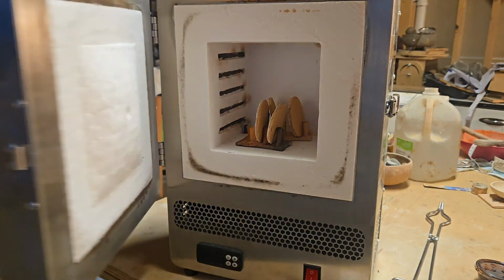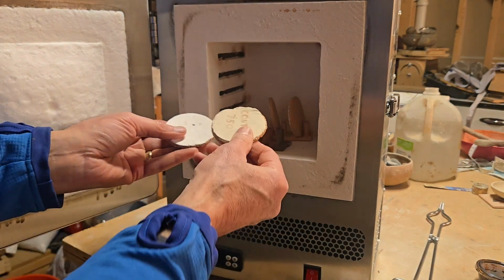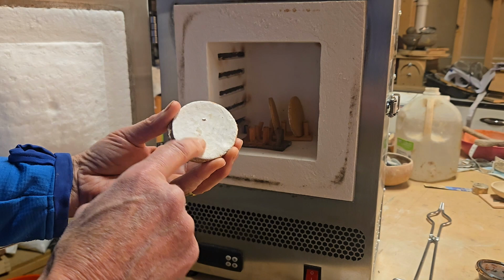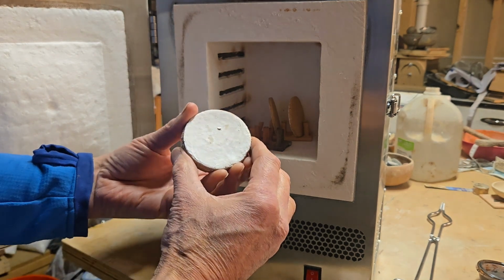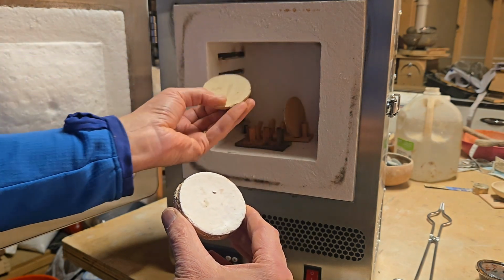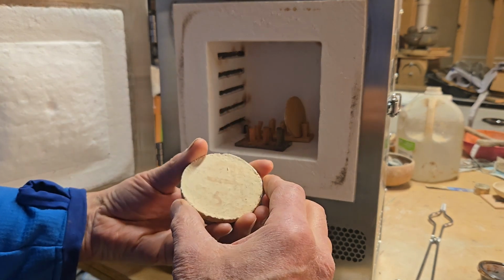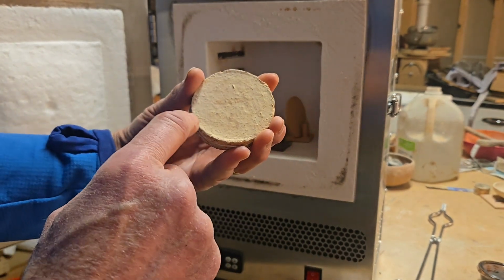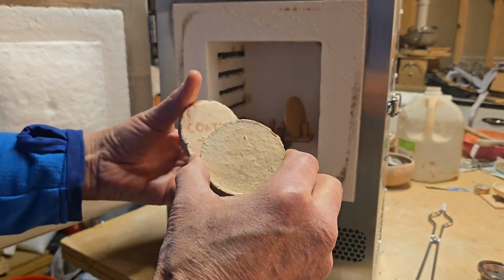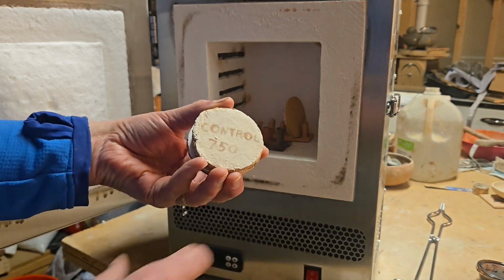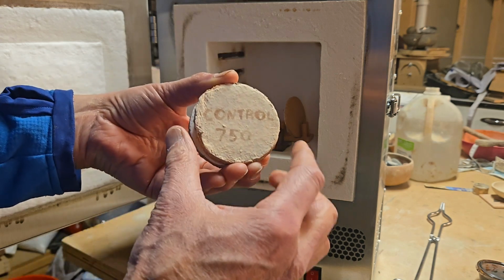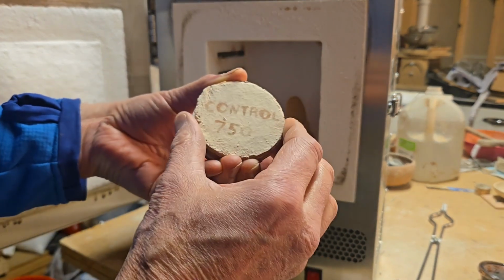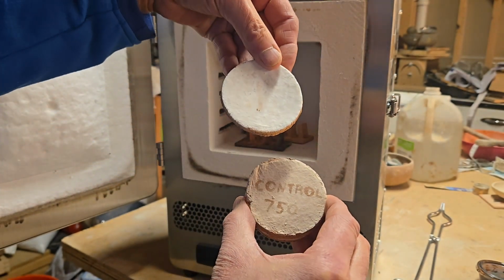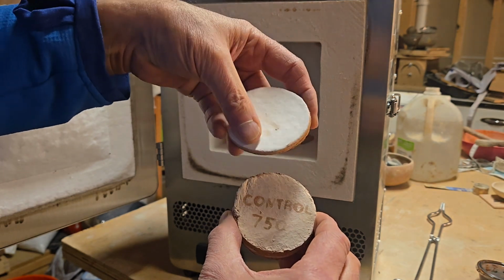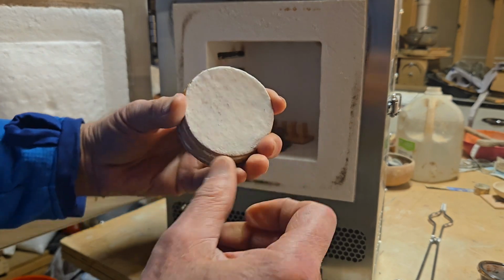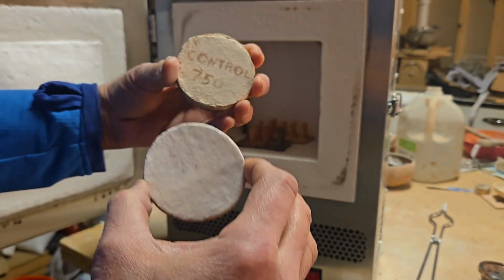Let's look at the tiles that were fired at 750 degrees. Okay, well, first of all, this is a tile with just plain white clay that was previously fired, so all of the organic paint burned off of that. Here is the other tile. This is smectite clay, and most of the paint burned off on that as well. So with the control ones, this is smectite clay, and it was unfired. It's an unfired tile, and I would expect it to be black, but it's there anyway. And if we look at the plain white clay, not smectite, there's nothing. It's gone. So one thing this does show is that smectite clay will absorb organic paint.